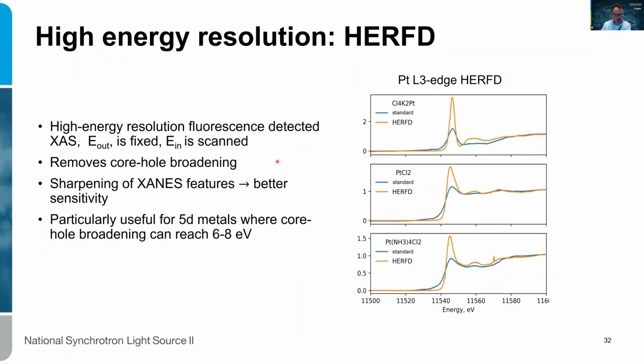Bruce is on the call. This slide, the next one was done with him, with the materials scientist Bruce Ravel. So this is just to show you the kind of improvement. This is the HERFD, the high energy resolution fluorescence detection, where we use, I'll show you, the curved optics instead of an energy discriminating detector or just a regular fluorescence or transmission detector. This is an enhancement that's due to the removal of the core hole broadening. It works especially well for 5d metals, but as you'll see on the next slide, also for first row transition metals, it gives you a much better sensitivity to the pre-edge features and the features in the white line.